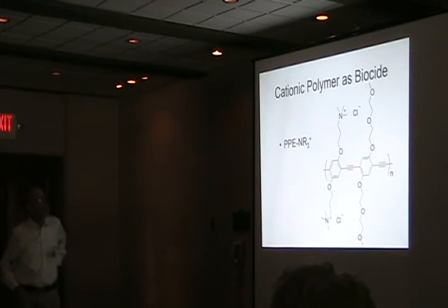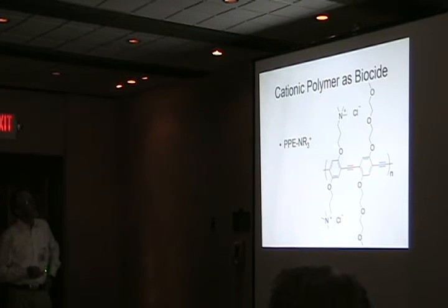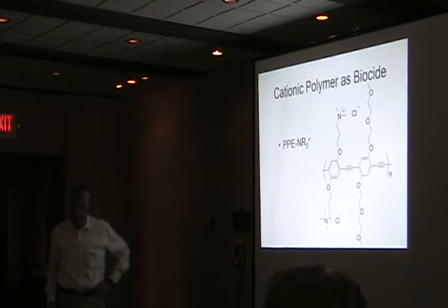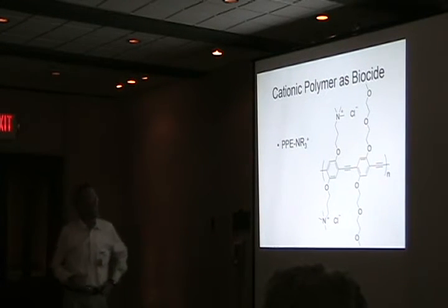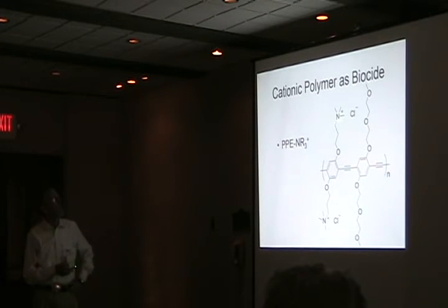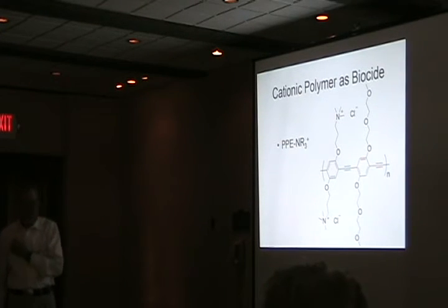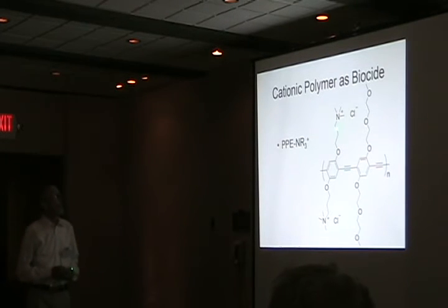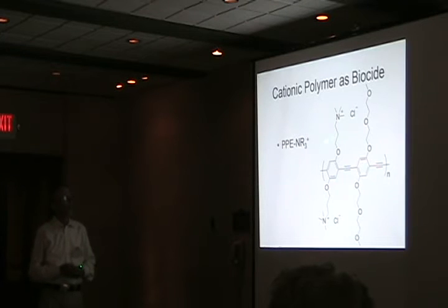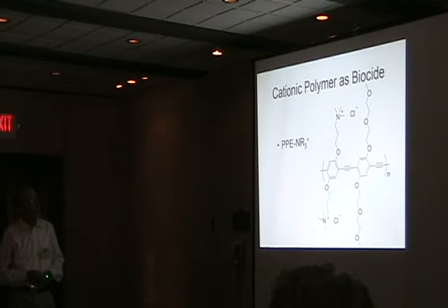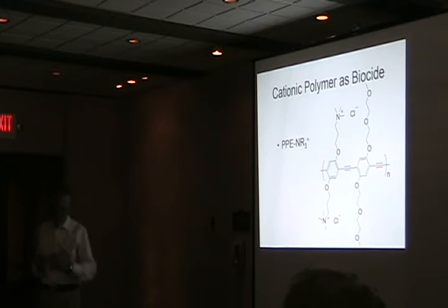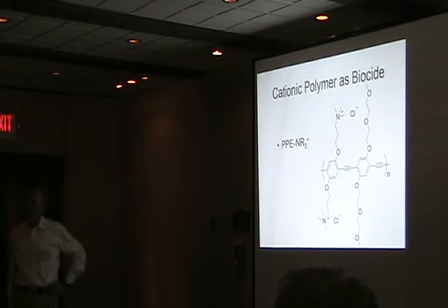Okay, the last thing I'd like to tell you about today is our work with the polymer as a biocide. We were initially interested in this polymer. This is a cationic polymer with quaternary ammonium groups. And we knew that a lot of quaternary ammonium surfactants are effective as biocides, and we thought maybe this would be the case. We also thought, since the polymer absorbs light in the visible, we might have a visible light enhanced biocidal activity. Well, in fact, what we found is that adding the polymer to suspensions of various bacteria and exposure to visible light did result in killing. We could also take the polymer on a microsphere support and expose it to suspension of bacteria, and we found there was some killing under those conditions.